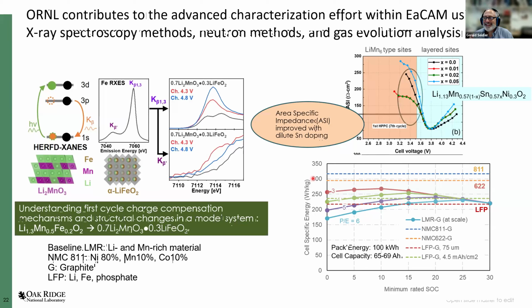Okay, so let's push that a step farther. You have the tin at the grain boundaries, but maybe the bigger picture is just that now the system is so nanotextured and there is a lot of grain boundary for lithium percolation. Is the effective surface through which the lithium can intercalate increased because of the extreme nanodomain formation? The nanodomains that we talked about, that we see in X-ray absorption, are a completely different length scale than the grains that you're seeing in the TEM.